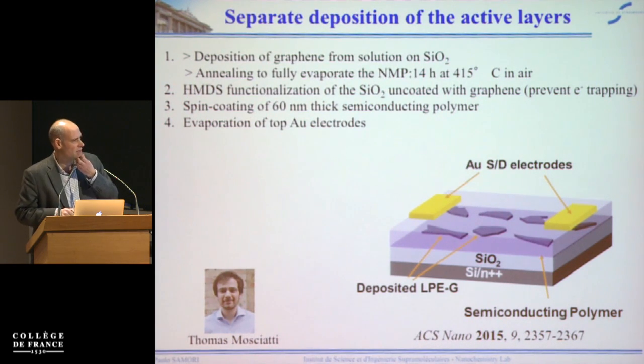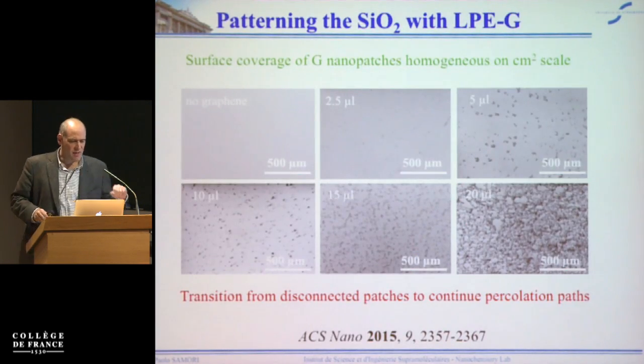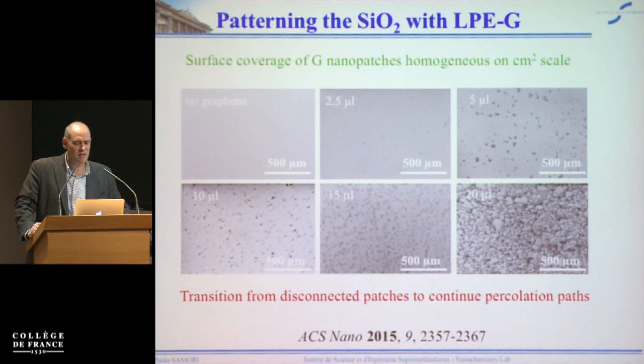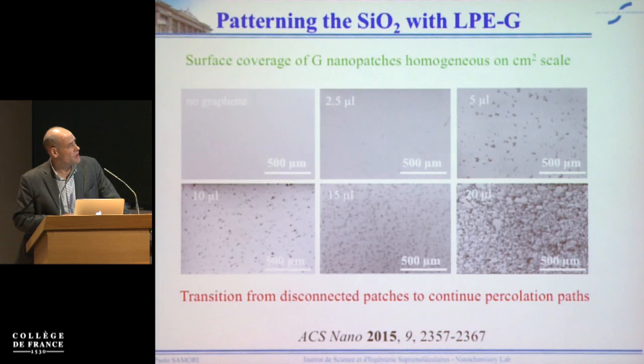So these are the source and drain electrodes. Now, depending on the concentration of the solution of the graphene that you deposit, you can have different types of, let's say, coverage of the silicon dioxide surface. You can go from no graphene, a purely silicon dioxide surface, to more and more densely packed surfaces with patches of graphene. Either you change the concentration or you change the volume, it doesn't matter.